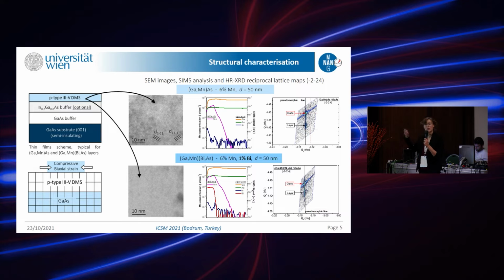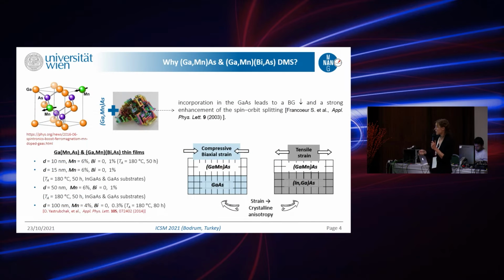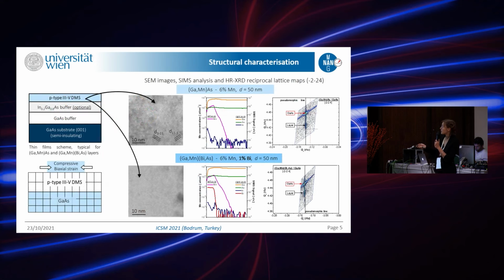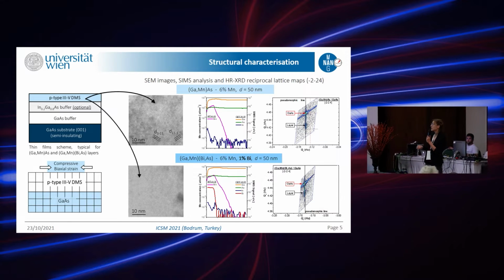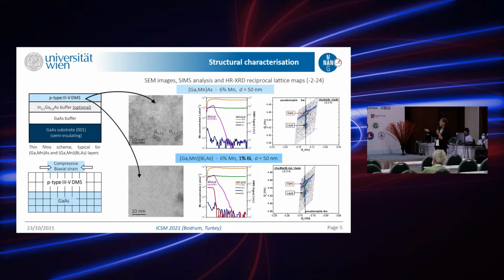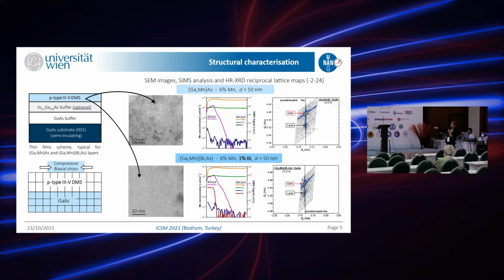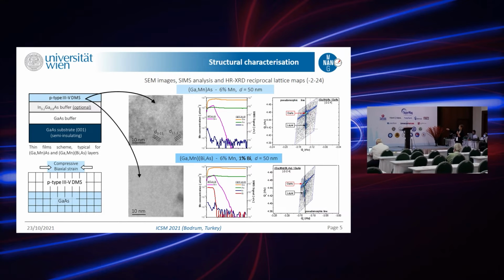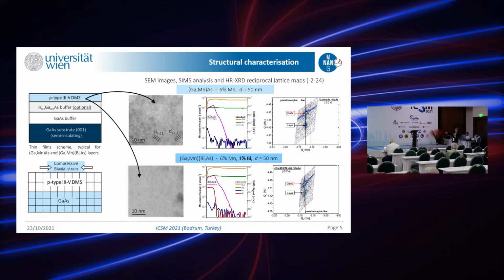Before proceeding to magnetotransport, I would like to prove that all our samples were of high quality, and for this you see the results from the SEM, mass spectroscopy, and high-resolution X-ray diffraction reciprocal lattice maps. The SEM shows no defects in the vicinity. The scale is 10 nanometers for both the ternary and quaternary compounds. The ternary is on top, the quaternary is on the bottom.